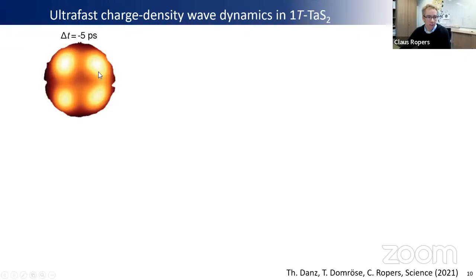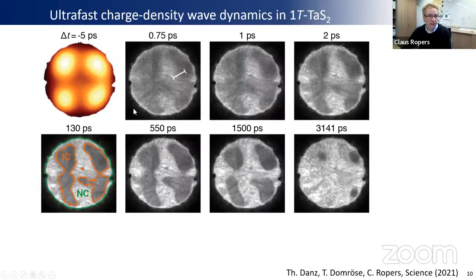This is the optical excitation profile, which we determine from reference measurements, essentially, such that the optical excitation incident here leads to scattering from the sides and leads to basically optical hotspots in this excitation here. And now we vary the delay. So we take a movie of the evolution of this periodic lattice distortion as a function of time and space, and obtain these snapshots here.